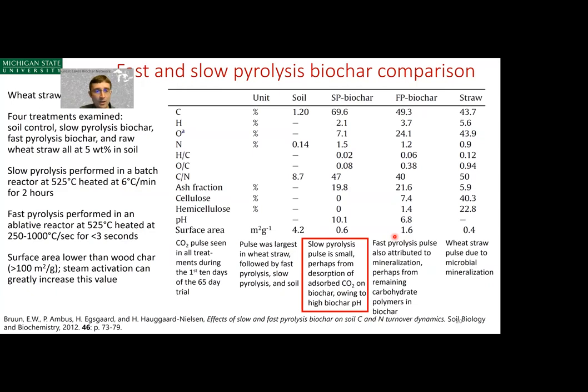The slow pyrolysis pulse did occur, but it was very small. The authors attributed this perhaps to some adsorbed CO2 on the surface of the biochar owing to its high pH. Bases are capable of trapping acids, and CO2 is an acid; when it's dissolved in water, it forms carbonic acid. So perhaps some of that CO2 was trapped on the surface and just liberated over the course of the first 10 days.